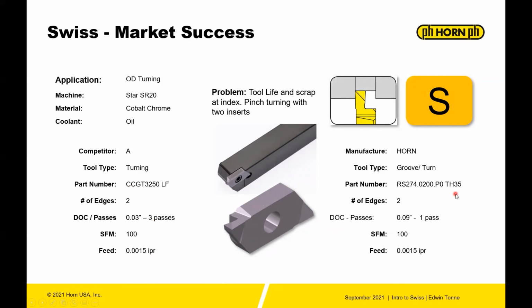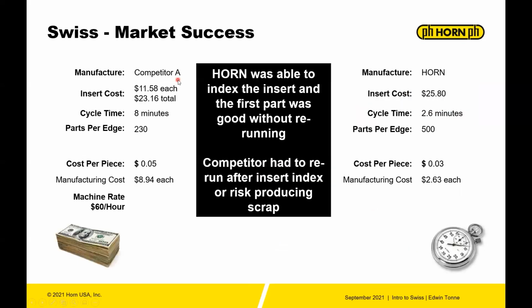The Horn product was a 274 with the turning geometry in TH35. We just took 1 pass, so all 90 thousandths in 1 pass, 100 SFM, and 1 thou 5/10 inch per rev. So same surface footage and same feed per rev. So the competitor tool cost, the insert was $11.58 each, but they had 2 inserts, so that's $23.16 total. Their cycle time was 8 minutes, and parts per edge 230. The Horn tool was $25.80. Cycle time was 2.6 minutes, and the parts per edge were 500.